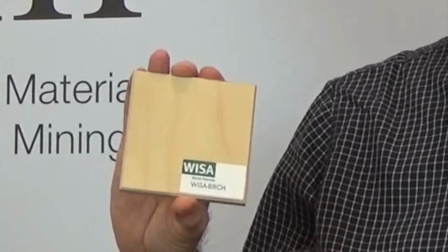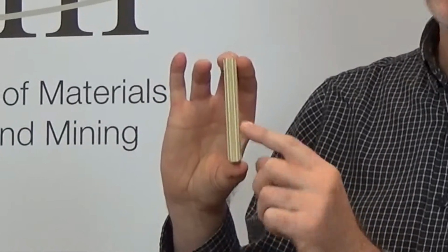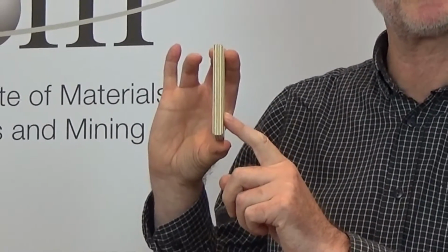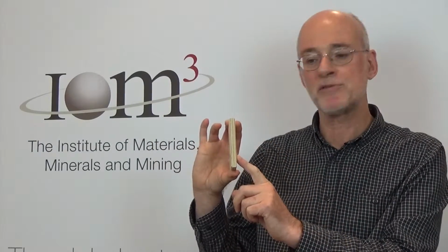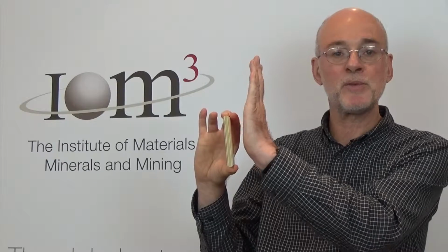So what's the incentive for making wood composite products? Well, here's a sample of plywood. And you can see on the edge section that it's made out of thin layers of veneer which are bonded together with a very small amount of adhesive. The idea here is that the grain runs in one direction in one layer and in the next layer at 90 degrees. So in the 2D plane of the product, we spread the properties in all directions.